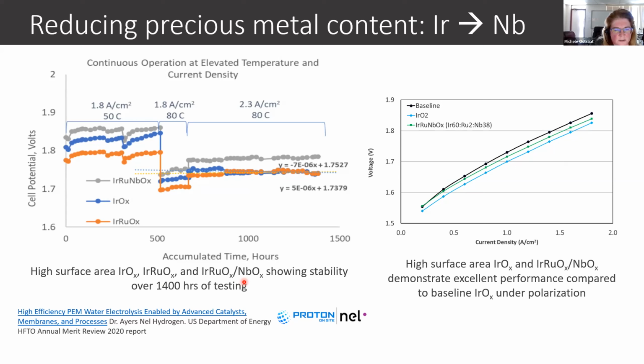the iridium oxide materials. On the right-hand side, we've got a polarization curve that's looking at the baseline material. This is a non-high surface area iridium oxide that's commercially available, not by Pajarito, but by another organization. And then the high surface area material that we make at Pajarito Powder, as well as some of our iridium and niobium included materials. And what you can see here is that our high surface area iridium oxide actually has the best performance of these, but our ruthenium and niobium containing materials also perform quite well.